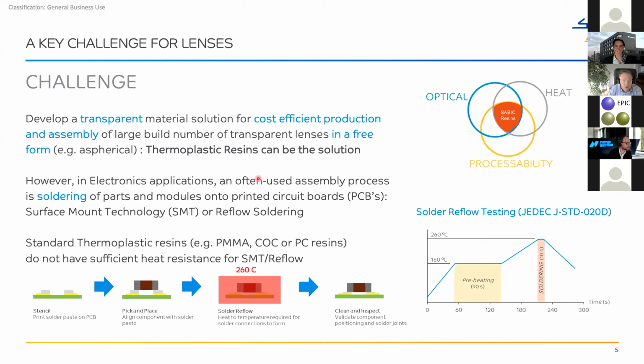In the semiconductor industry, an often used assembly technique is reflow soldering. So that means that the lenses need to survive reflow soldering, which is another word for surface mount technology. And for those of you who do not know what that is, it is depicted on the bottom of this page, where the components are put on the PCB with a solder paste. And then, because solder pastes these days are lead-free, you need to go to a pretty high temperature. I think this is the typical JEDEC protocol, that you go from room temperature to 260 degrees for 10 seconds, which of course is very harsh for most of the standard optical polymers like PMMA or COC or PC.